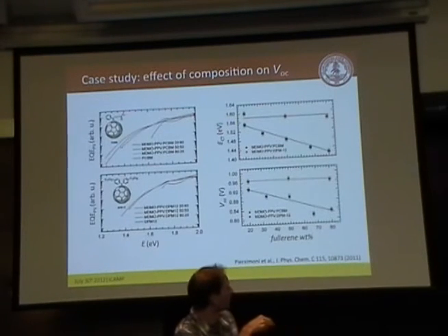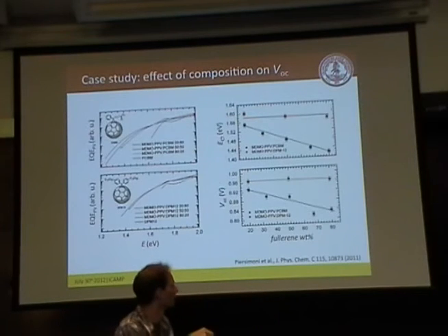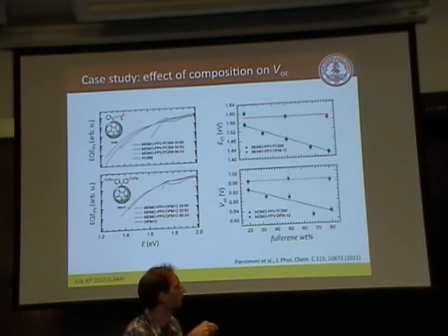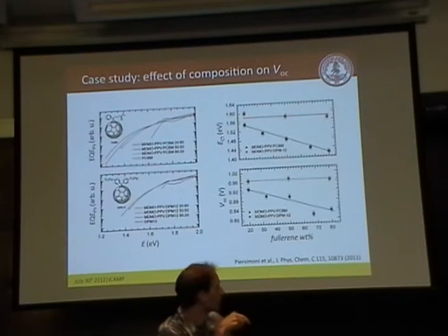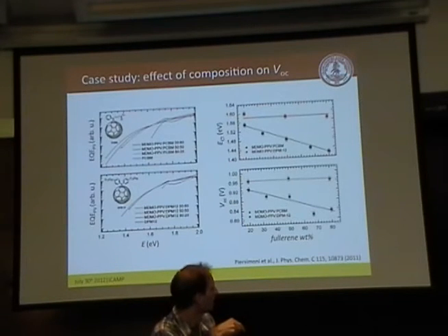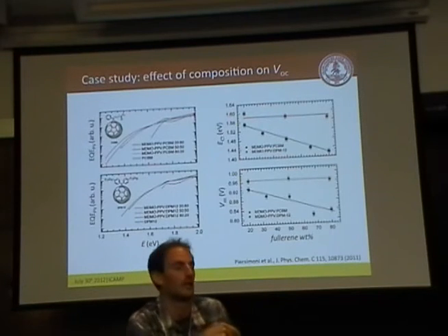Well, we did the same experiment with this fullerene. It's not PCBM, it has something really long, a C12 here, so it has long side chains. If you spin-coat pure films with this molecule, it does not like to crystallize as much as PCBM does. We're not even sure it really does form fullerene aggregates. What happens here is the energy of the CT state does not change, or not change much, if you add more of this one. And you see VOC stays high too. The thing is, this doesn't crystallize, so unfortunately we couldn't keep the high current that you had for PCBM. So overall, this fullerene acceptor is worse for the whole solar cell. It's better for VOC.